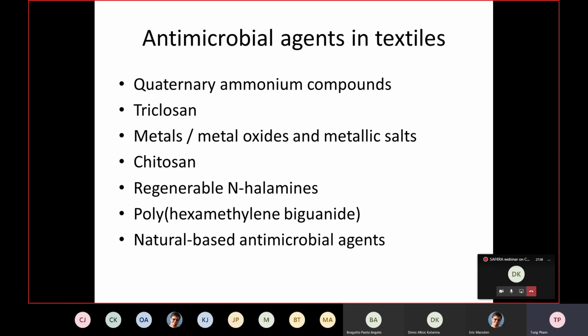Chitosan is a natural and hydrophilic copolymer. The way it acts, as generally accepted, is that the first step is based on the interaction between the primary amine groups, with positive charge, and the negative charges on the microbe surfaces. Then chitosan can penetrate into the cell wall, combine with the DNA, and inhibit the synthesis of RNA, preventing protein synthesis. It also has some problems in handling, depending very much on the temperature and pH, which is also very critical for the stock, which is chitosan.